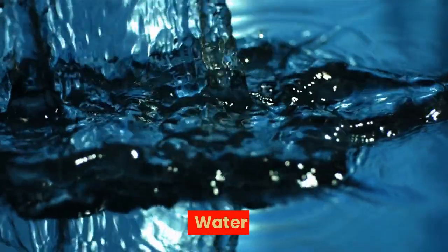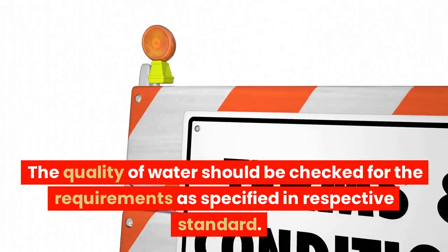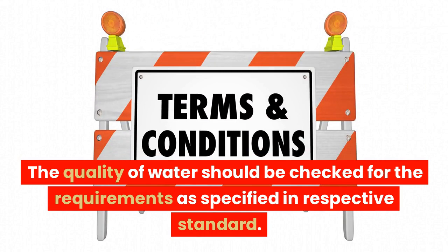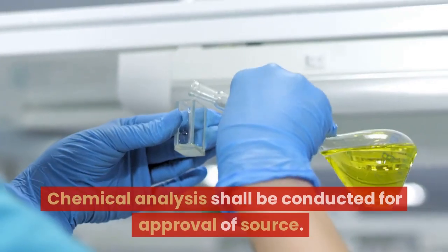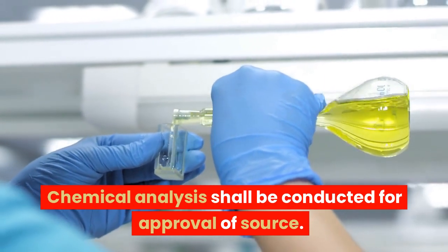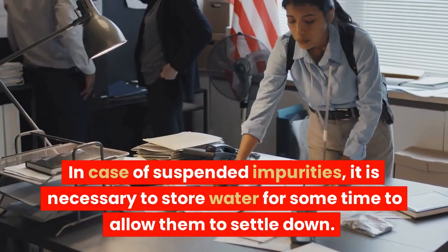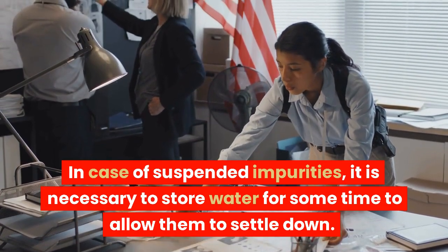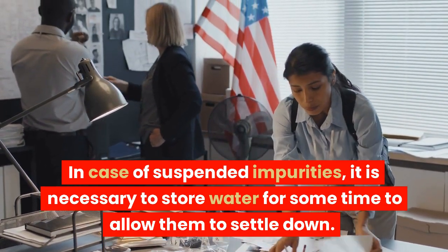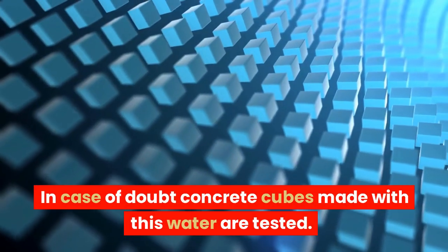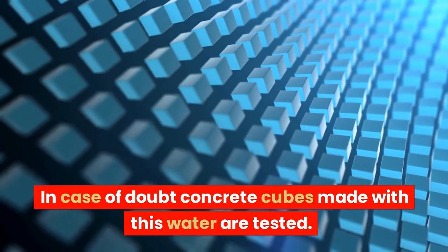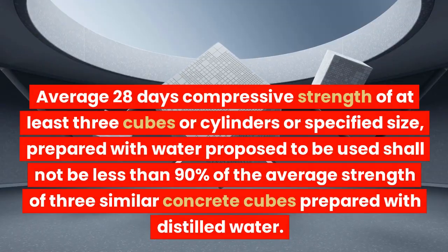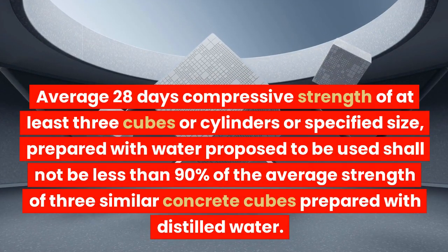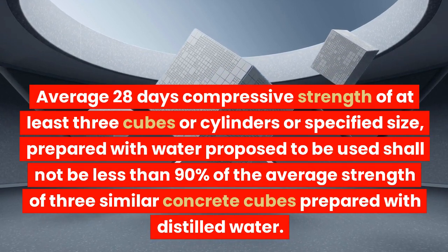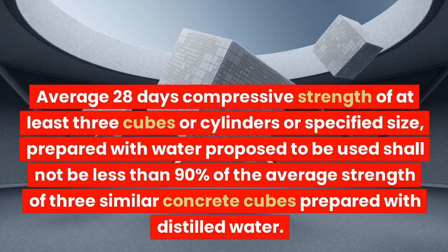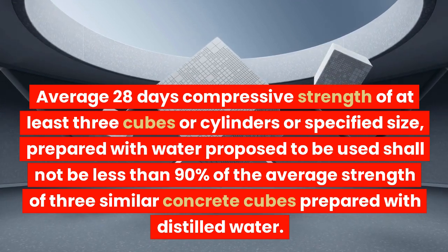Water. The quality of water should be checked for the requirements as specified in the respective standard. Chemical analysis shall be conducted for approval of source. In case of suspended impurities, it is necessary to store water for some time to allow them to settle down. In case of doubt, concrete cubes made with this water are tested. Average 28 days compressive strength of at least 3 cubes or cylinders of specified size, prepared with water proposed to be used, shall not be less than 90% of the average strength of 3 similar concrete cubes prepared with distilled water.